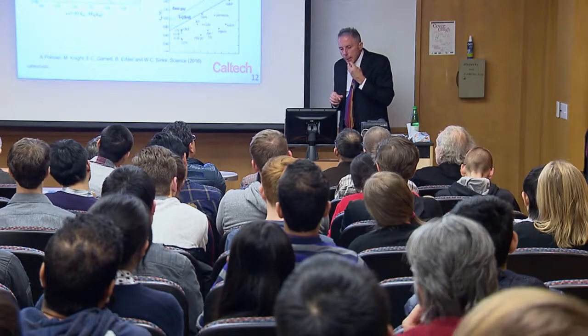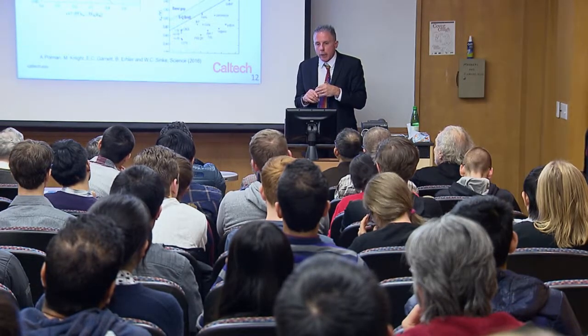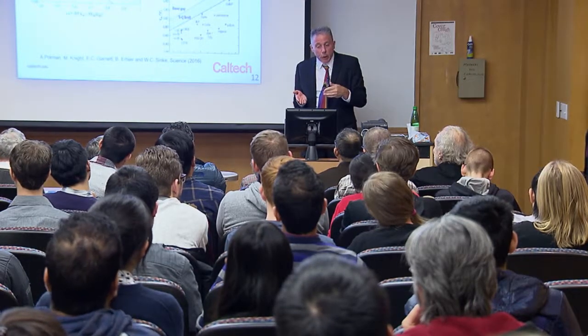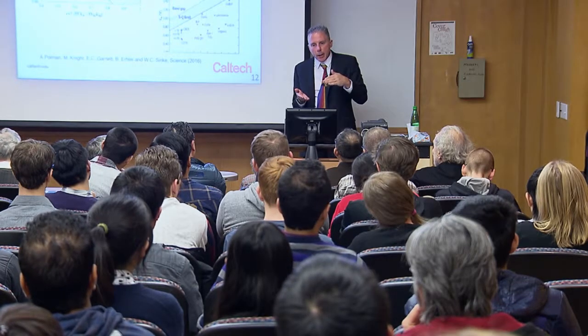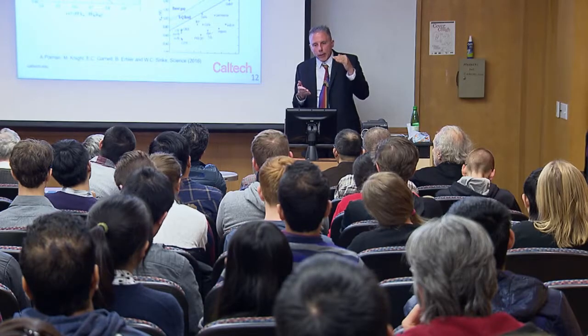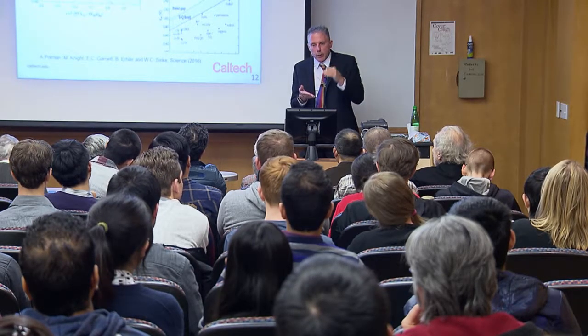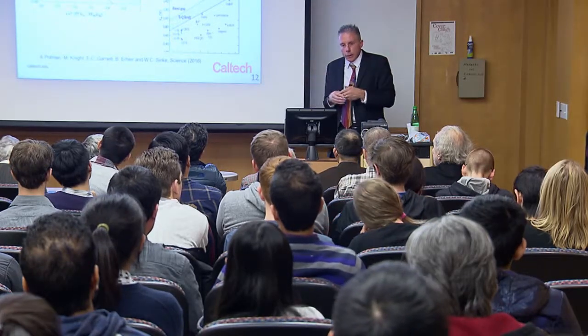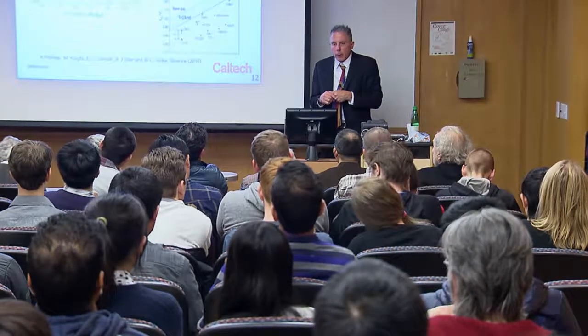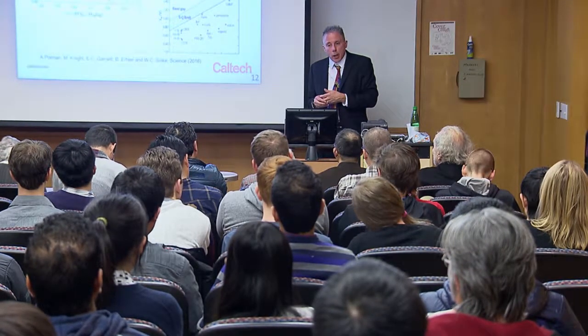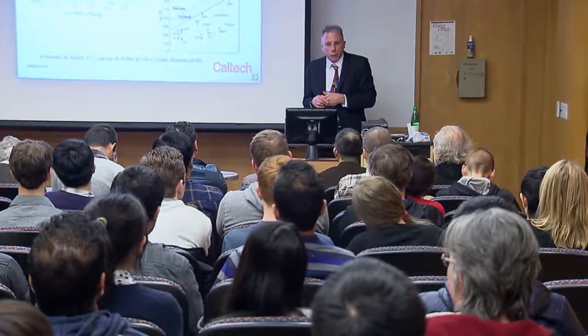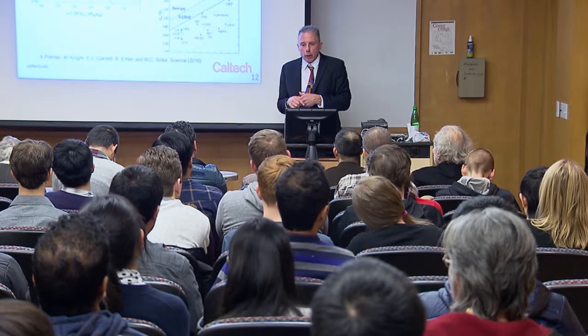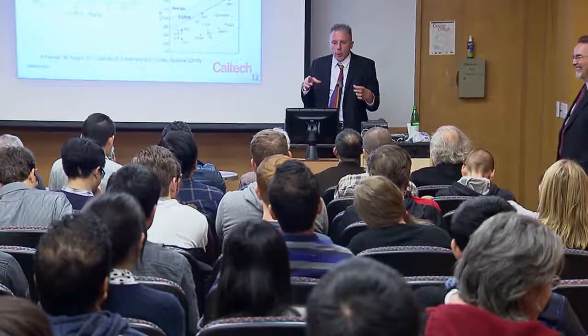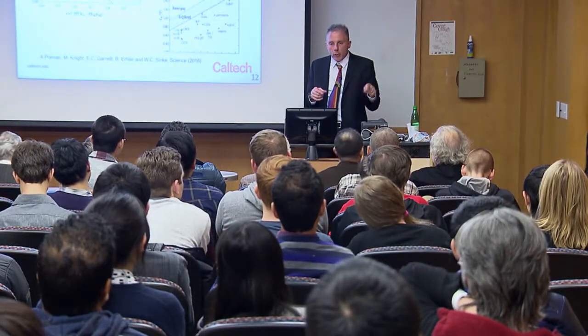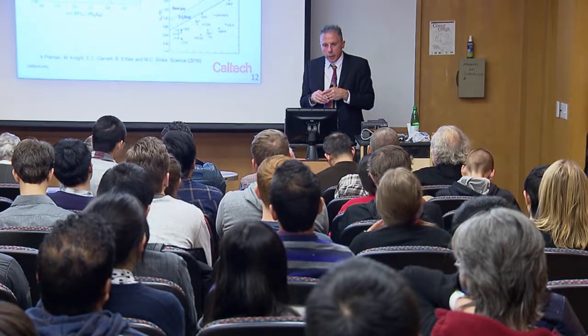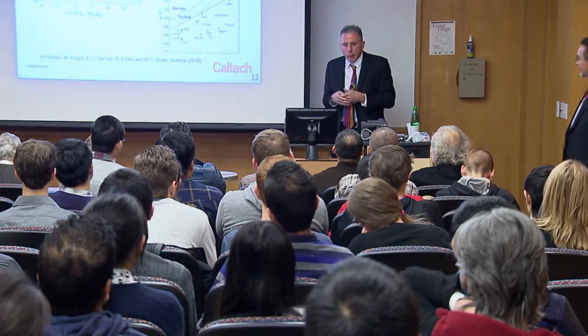So you asked about gallium nitride. Gallium nitride by itself has achieved very high radiative efficiencies. The challenge is that the gap is quite wide. We can alloy with indium, for example, to bring the gap down, but so far when you do that, the radiative efficiency doesn't hold up quite as well once you get it down into the useful range. So I think the jury is out—it may come to be useful. Certainly we're going to see nitride LEDs on our phones. Actually, one of my students went to work for Apple, and he refused to tell me what he was working on, but I figured it out anyway—it's visible nitride LED microdisplays. So I think we're going to see that technology for very high radiative efficiency gallium nitride driven even further.